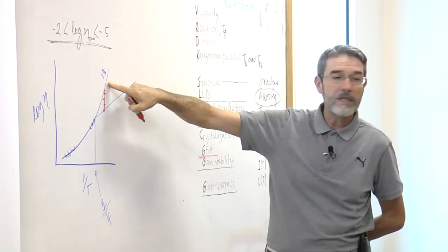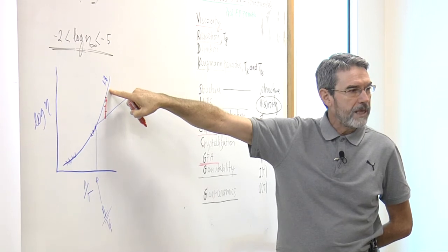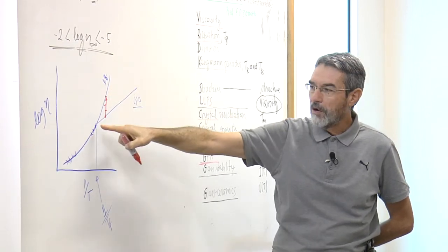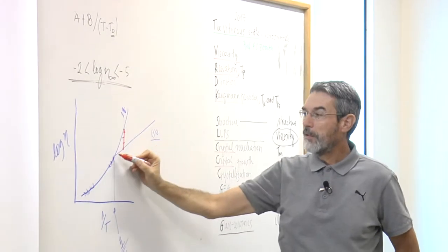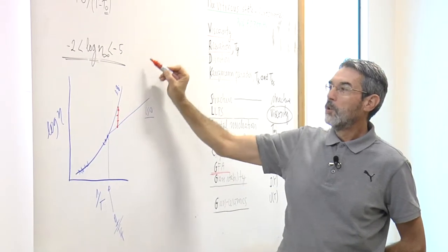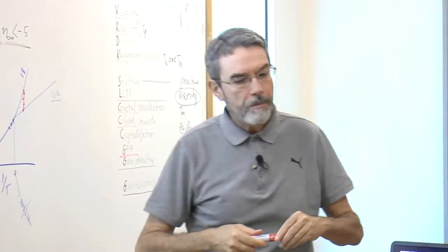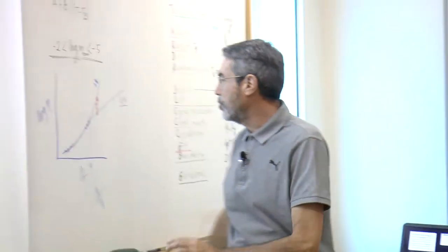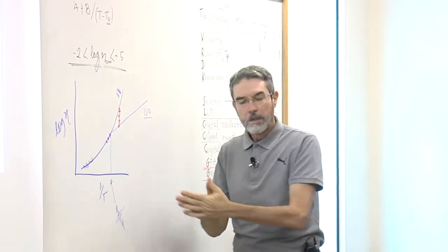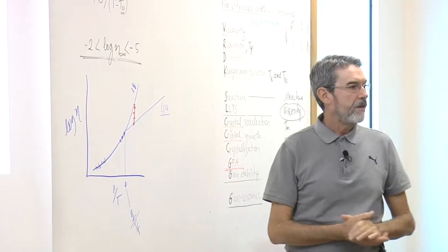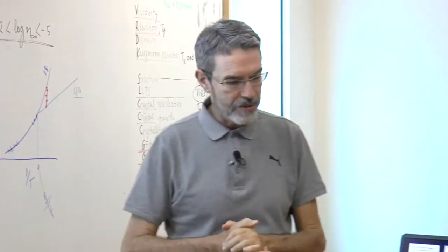That's why it's very important to know which equation we have to use, because as I told you, the Vogel-Fulcher-Tammann will lead this to infinity, and other equations will lead to other values. So it's still an open problem. Which equation can be used to extrapolate the viscosity below the Tg or the fictive temperature? It's not clear yet. There's discussion in the literature.